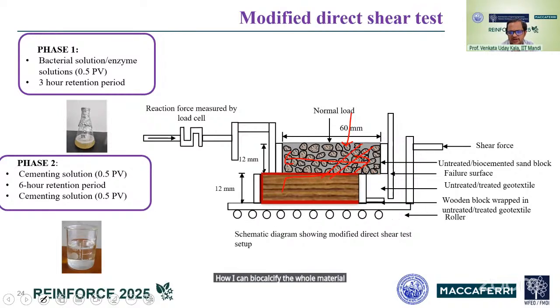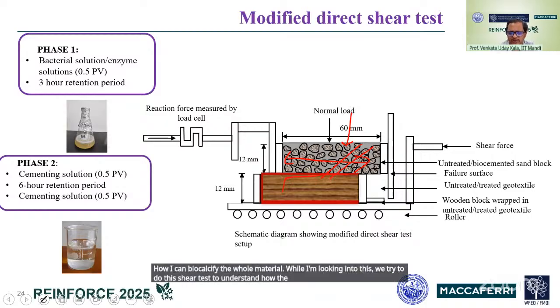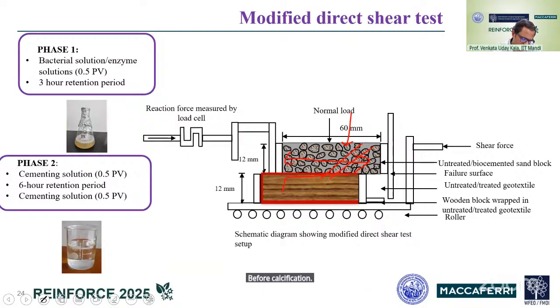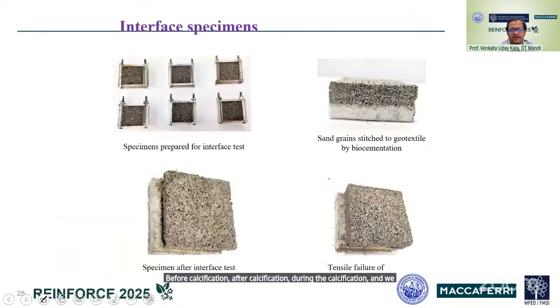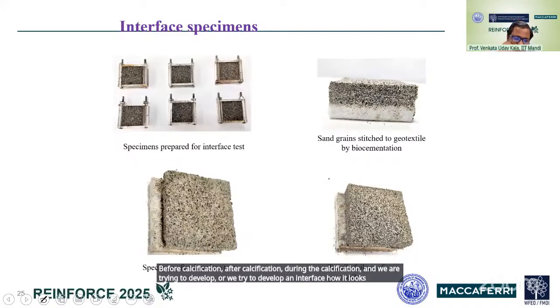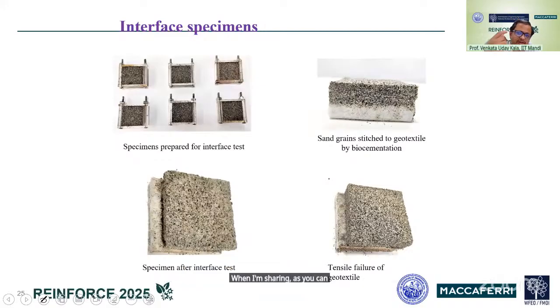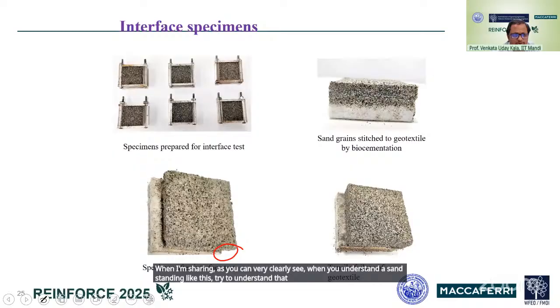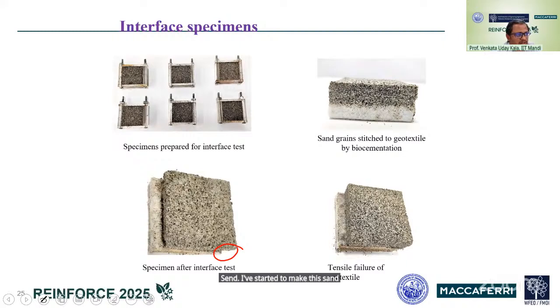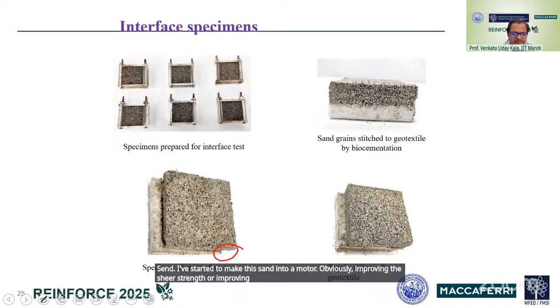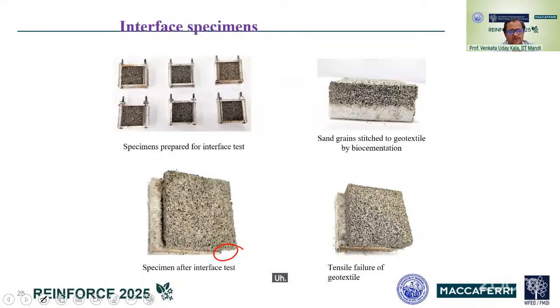While I'm looking into this, we try to do this shear test to understand how the interfaces are improving over time, before calcification, after calcification, during the calcification, and we try to develop an interface, how it looks something like this. As you can very clearly see, the sand standing like this, try to understand that this bacteria which I have put into the sand have started to make this sand into a mortar, obviously improving the shear strength or improving the interface conditions of the material. Again, to start with, we talked about a poorly graded sand, which has now been converted into sandstone, possibly, and improving your interface.